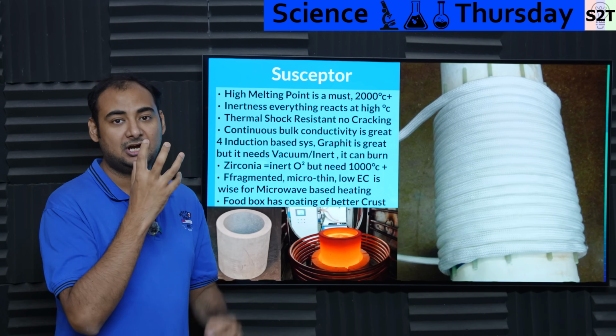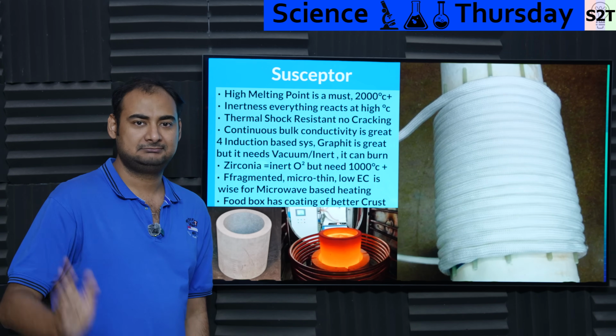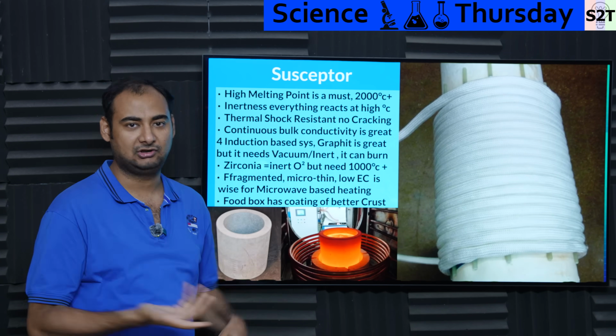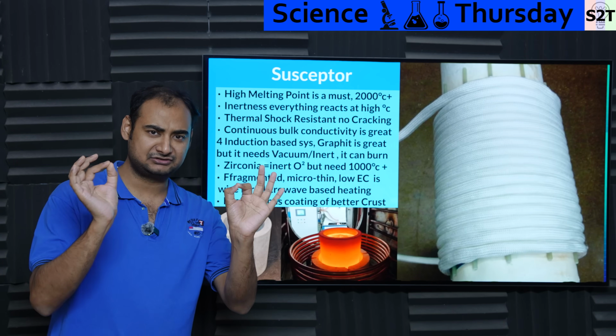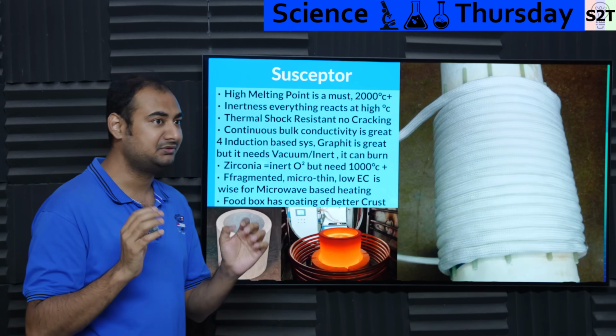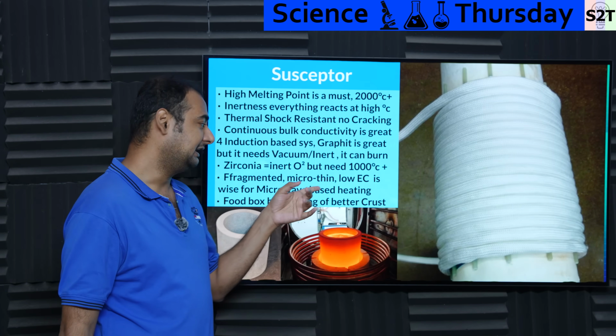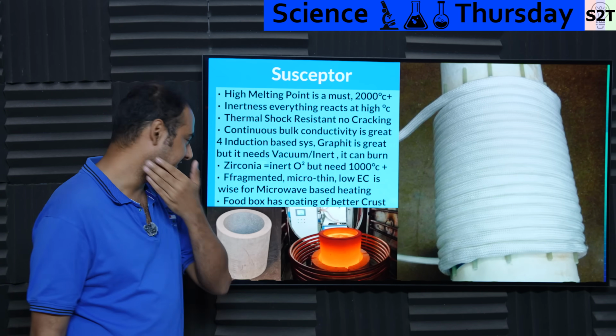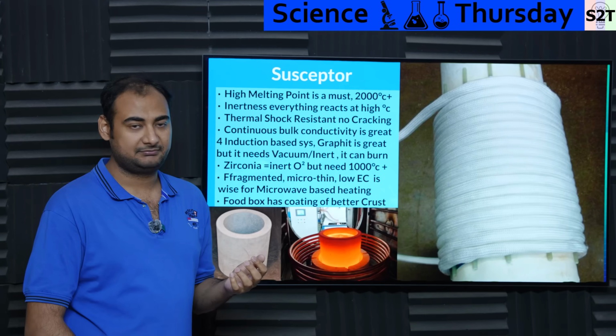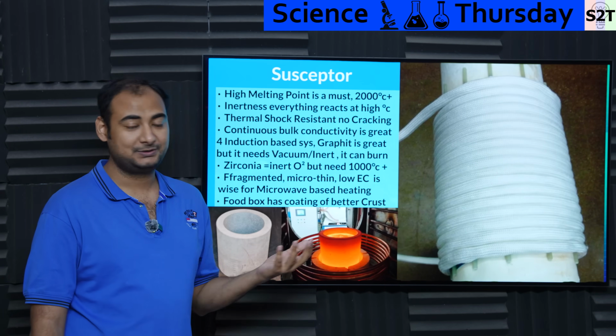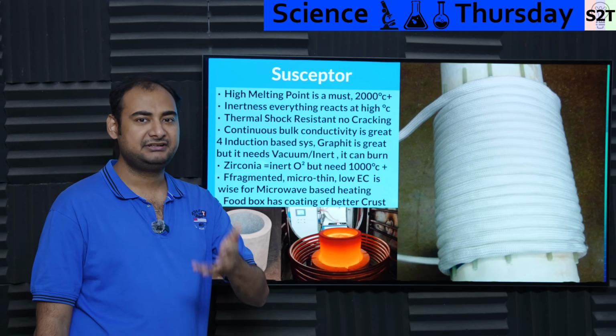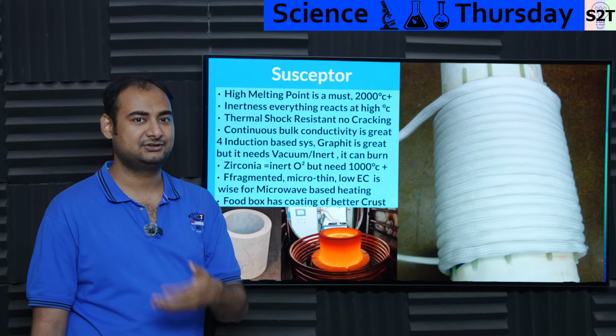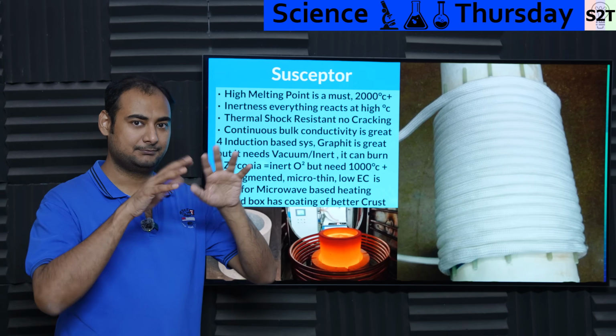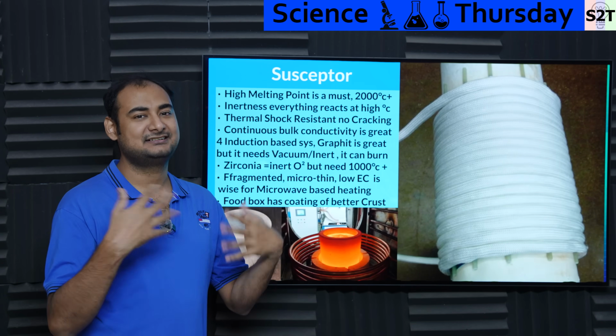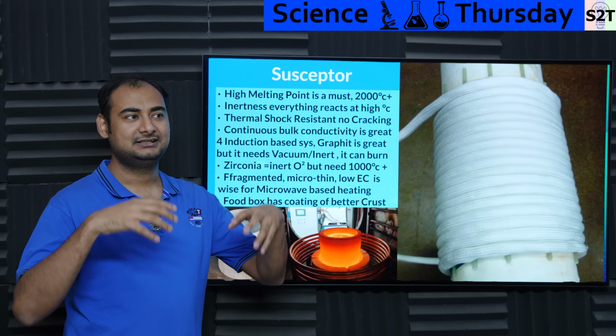For example, if you put in an aluminum bucket, it will just do nothing. Nothing will happen. But if it's micro thin, like microns thick, it will heat up crazy. Basically you need low electrical conductivity for microwave-based heating. Now we do use that. It's super easy technology. You may have eaten food from a box that was designed to go into a microwave, and that box, that could be cardboard, has a coating inside it that cooks it.